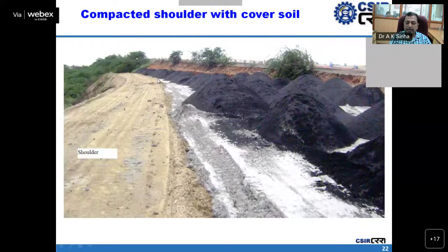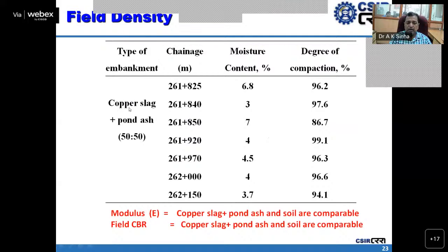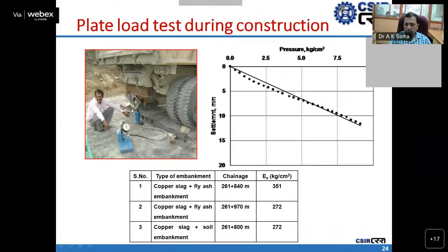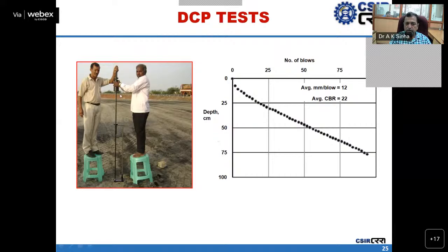So this is another. You see, it is a frictionless material. So to protect against erosion of the slope, locally available soil was used to protect the slope of the copper slag fly ash embankments. This is the existing ROB approach road. And during the construction, layer by layer, each layer density was measured, and it was found that it is coming more than 95% as per the IRC guidelines. During the construction, the modulus of the embankment layer was also determined by using plate load test, and field CBR was also determined using DCPT test.